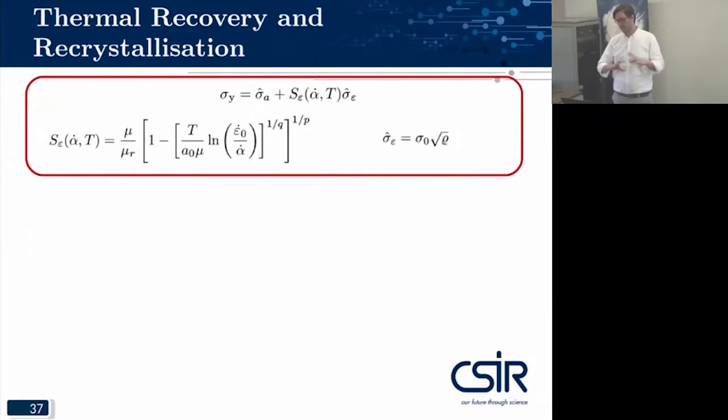So essentially what I have is I've taken a lot of the basics, so we have this formulation. I've removed one of the components of the mechanical threshold stress just to reduce the amount of parameters to tune. And now my internal state variable, which evolves as a function of deformation rates and temperatures, I've chosen a slightly different representation of it, where it's compared to an original, or stress-free, dislocation density ratio within the material itself. And then I have a dislocation density ratio internal state variable.